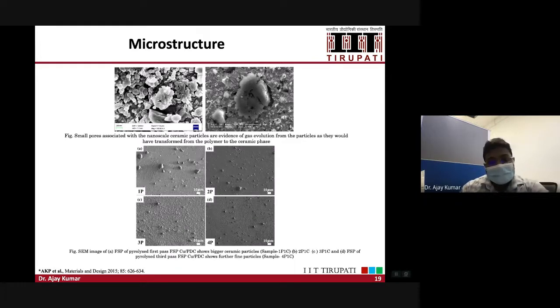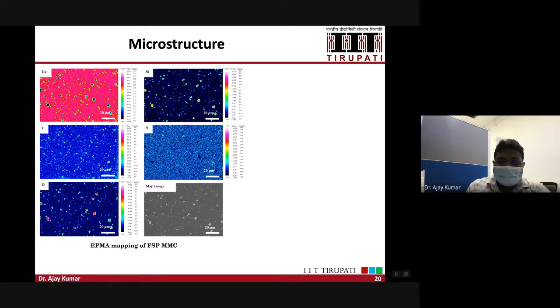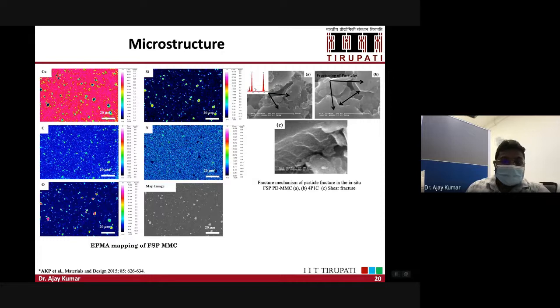Then we did the multi-pass processing on the same porous materials and redistributed the ceramic particles, and we again did the multi-pass process, and you can see there are no voids, but you can see the distribution of these PDC particles inside the matrix. Okay. To further study and understand the distribution of the PDC particles, we did the EPMA mapping. All the elements are present. Okay.